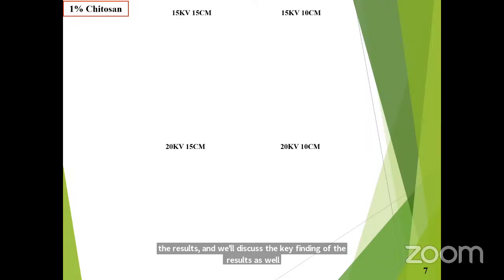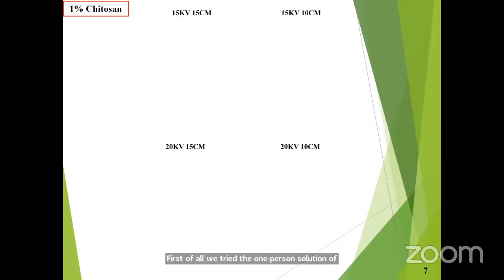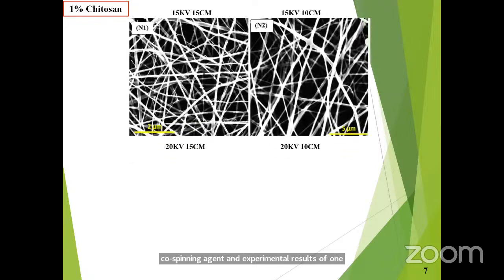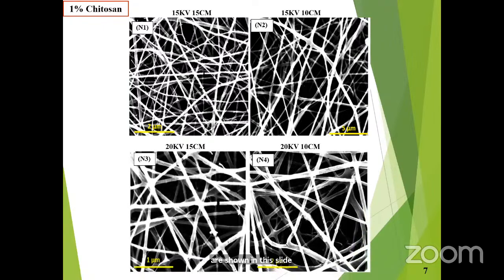First of all, we tried the 1% solution of the chitosan to produce the nanofibers by using the co-spinning agent, and experimental results of 1% chitosan nanofibers at two different working distances and high voltages are shown in this slide. All four samples showed smooth chitosan nanofibers without beads.